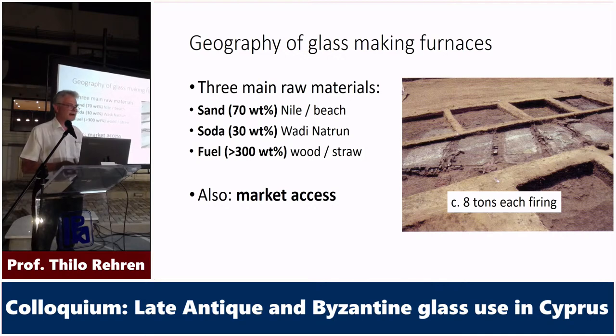That 1 month's worth of firing of your 8 tons of glass, you burn many, many tons of wood for that. And that's even more difficult to ship and to transport, not only because of the multiple in weight, but even the multiple in volume, because wood is pretty light compared to sand. So you will actually make glass where you have fuel, such as in the mountains of the Lebanon, or at least agricultural waste from the fertile Nile Delta. Straw, very quick and hot burning stuff that gives a nice flame and heat radiating onto your mixture to melt it.